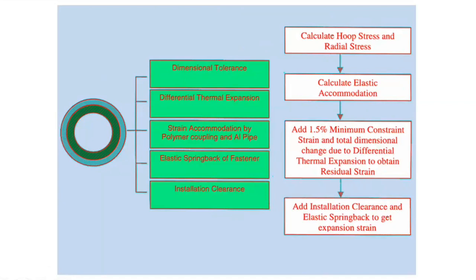Just for the interest of people, you start with 6% strain, and that's all you got. I say the most difficult part is strain accommodation with the polymer. The polymer sinks because it's an elastomer, and it has to transmit that stress. The strain is transmitted through this polymer onto this interface, and that is a holding stress. If it was very hard, it would not have transmitted. It has to transmit it.